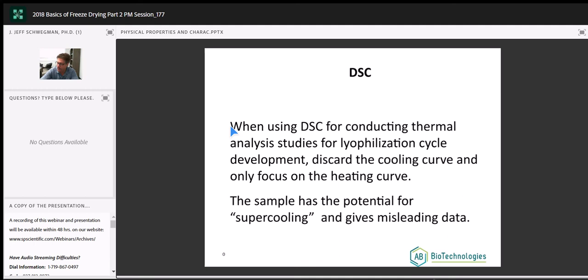Now, when using DSC for thermal analysis, we get two curves that are generated. One, the cooling curve. We start at room temperature, we cool down, we have a curve for that. We warm up from that frozen state, we get a warming curve for that. Now, we don't use the cooling curve other than looking at it. The issue is, things always melt at a very precise temperature. Things do not always crystallize or freeze at a characteristic temperature. So we kind of have to take that with a grain of salt, and the best way to show this